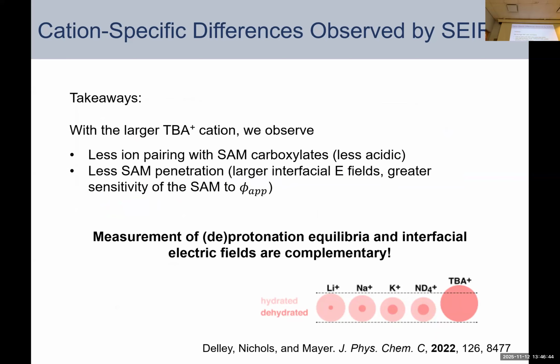And I think it's interesting and illustrative to bring in your intuition here. This really greasy, bulky cation is going to be less Lewis acidic, and so it makes sense that the carboxylate, or the carboxylic acid in its presence, is also going to become less acidic. And we also saw less SAM penetration of these cations with the larger, bulky and greasier tetrabutylammonium cation. So what I hope I've been able to share with you from those several examples is that here we've been able to look at deprotonation equilibria and also interfacial electric fields and get complementary perspectives on a fairly complicated electrolyte interface.